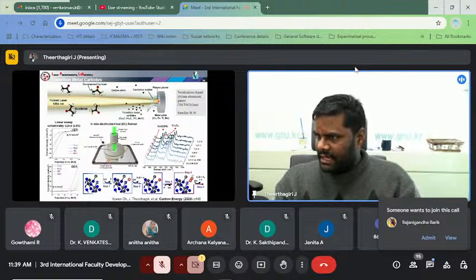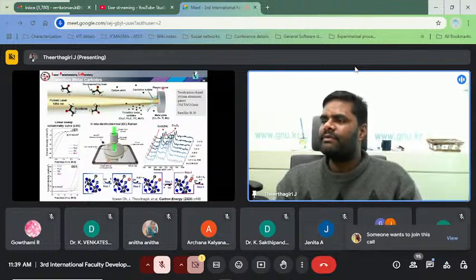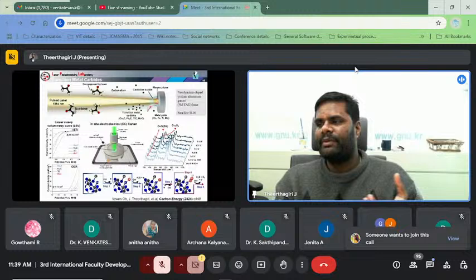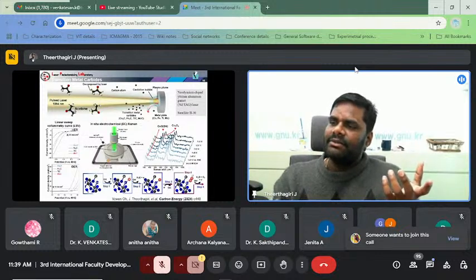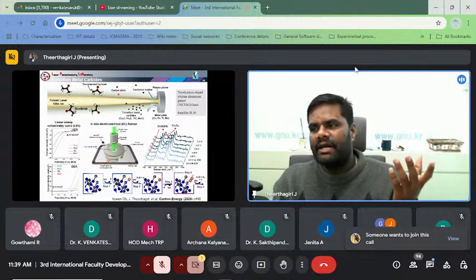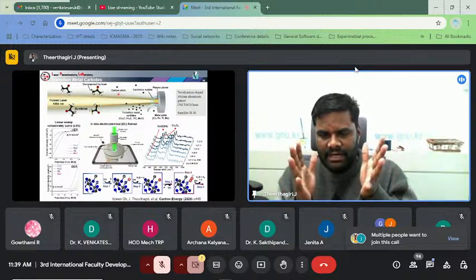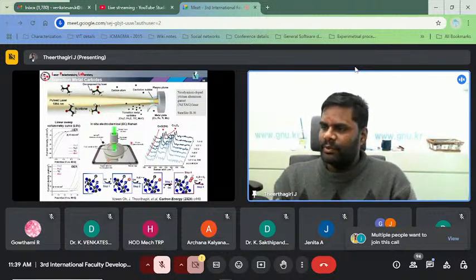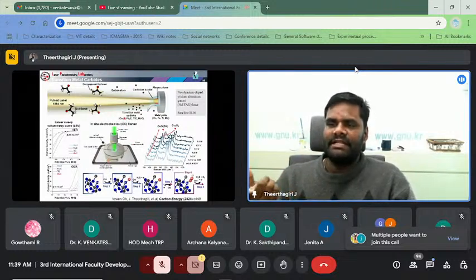When the laser heats a particular place, it produces a plasma at high temperature. It can produce the metal ions. Already in the laser path, there is acetone. It decomposes and produces carbon fragments or carbon atoms. These bind with the metal ions and produce metal carbides within 10 minutes. That is the beauty of our synthetic route.